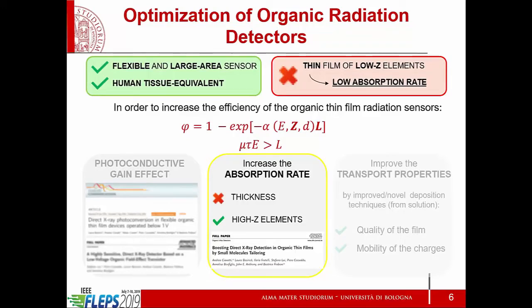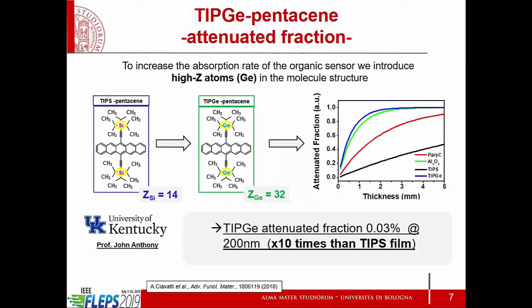So the idea is that we're not adding extra nanoparticles or elements, making it a blend. We leave it a pure small molecule organic film, but basically we use TIP germanium pentacene instead of TIPS. So what John Anthony from the University of Kentucky did was simply to substitute the silicon atom with the germanium atom in the molecule. The result is very interesting if you look at the attenuation fraction in the graph on the right-hand side. You see that by swapping the silicon atom with the germanium one, the absorption coefficient and the attenuation fraction go up very, very much. So we have about an order of magnitude higher attenuation fraction.